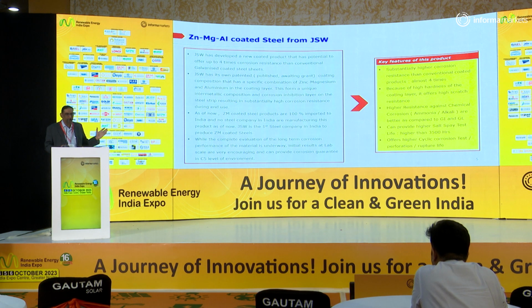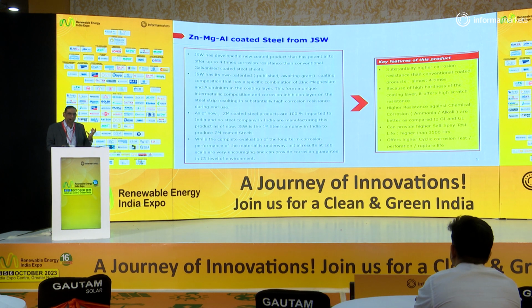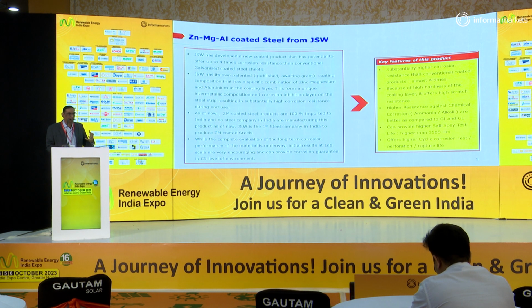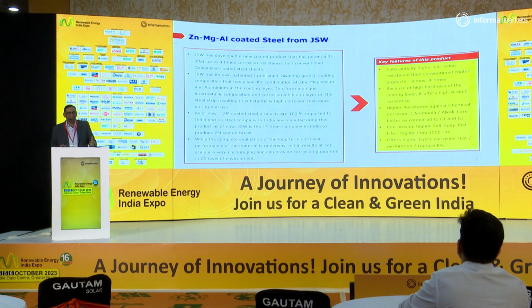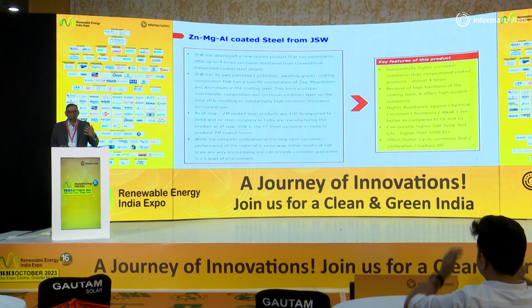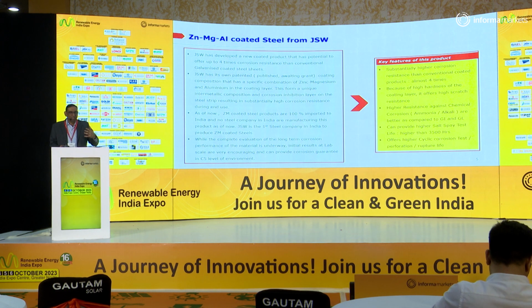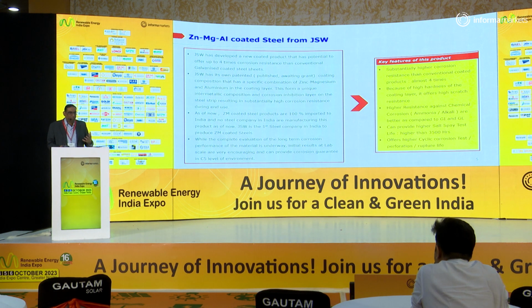And this product we have tested in our lab, and we have found out that this is suitable for that particular environment also. This product is having good scratch resistance. This product has got good alkali and acidic fumes resistance also. Overall, this particular product is basically imparting steel a kind of life which is required for the solar industry. The solar projects are designed to last for 25 to 30 years. Till now, we didn't have this kind of product in India. But based on our results, based on our research, we are quite confident that this can last for 25 to 30 years.